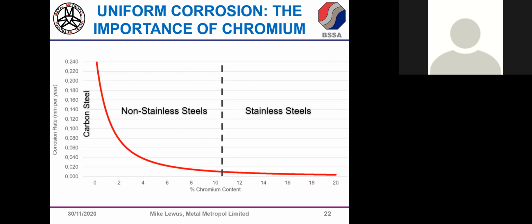So I'm going to deal with just the three that I mentioned mainly, but I'll just mention something about uniform corrosion first. As far as uniform corrosion is concerned, it's the chromium that is a big factor in preventing it. This plot shows corrosion rate, and I'm not going into the details of how these corrosion rates are being measured, but it's corrosion rate versus chromium content. And you'll see that cutoff, 10.5% chromium, which I said was a minimum amount that had to be in a steel we call stainless steel.